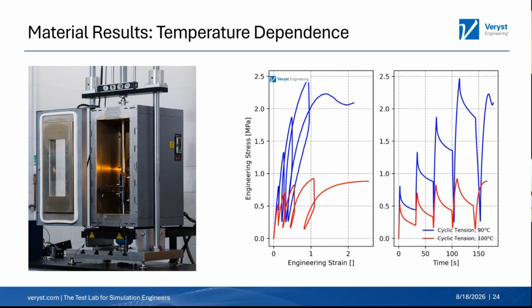And the other thing that I like to point out is by doing this one test, we've gotten stress relaxation data at multiple levels. We've gotten unloading at multiple levels. And that's important because as we do this type of thermoforming, we don't have a uniform deformation in the field. In the part that we're making, we have variable deformation where some areas have been stretched a lot and thinned out a lot, and other areas have not been stretched. So understanding how those are going to relax is going to be important.